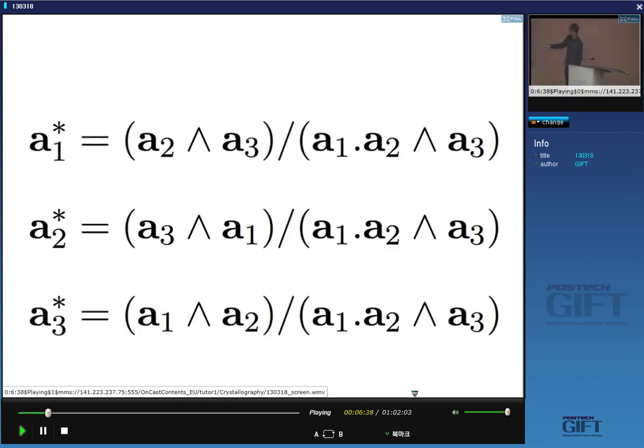And similarly, A2 star is at 90 degrees to A3 and A1 and has a magnitude which is the spacing of these planes, and A3 star is similarly defined. Now, obviously, the order in which we do this dot product is not important. If I had A2 dot A3 cross A1, that would be the same because it's still defining the volume of the cell. Okay, so this is a definition of a reciprocal lattice unit cell corresponding to every real space unit cell.